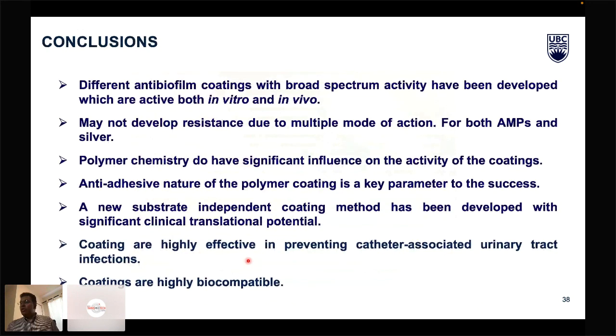So in conclusion, although I had to go a little faster to finish, what I have shown here is the criteria for generating an antibiofilm coating, starting from a polymer layer and then attaching antimicrobial peptides. We were able to arrive at certain criteria, showing that an excellent coating can be developed. And because we are using antimicrobial peptides as well as silver, the chances of developing resistance are going to be really low here. I won't discount that there might be a chance, but it is really low.